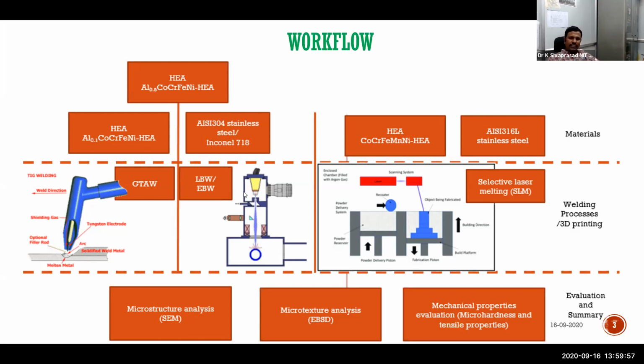Then he started working on TIG welding and laser beam welding. And on the other side, he started working on powder bed fusion, such as selective laser melting, using a laser to melt the powder. Then on all these welds and additive manufacturing components, he has done extensive microstructural evaluation, followed by microtexture analysis, because I am basically a metallurgist, so I always want to know what is inside the microstructure, what is inside the grain, what are the precipitates. This kind of interest is there for me, so we have gone for detailed characterization. Then regular microhardness profile, tensile properties, and other correlation techniques.